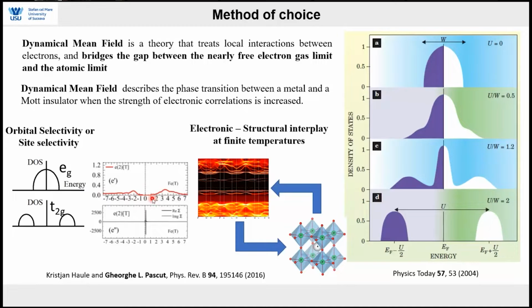But something I want to explain here is that you have systems like semiconductors, silicon or others, where you have a gap, but the electrons are of s and p type, and you don't have correlations. So that gap is called the band gap. You can still use DFT to explain that material. And the gap there comes because you have a particular number of electrons such that all these bands are occupied, you have a gap, and all these bands are empty. So that's called the band gap.